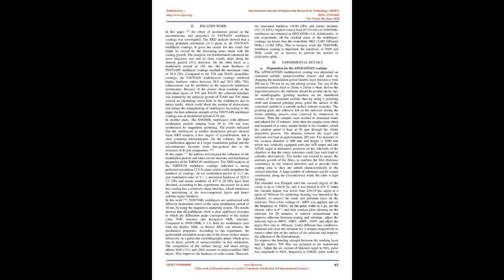In another study, the HfN/HfB2 multilayers with different modulation periods ranging from 20 to 150 nm were synthesized by magnetron sputtering. The results indicated that the multilayers at smaller modulation periods showed weak XRD textures, a low degree of crystallization, and a clear columnar microstructure. On the contrary, the high crystallization appears at a larger modulation period and the microstructure becomes more fine-grained due to the existence of B-rich components. 16. In this paper 17, the authors investigated the influence of the modulation periods and ratios on the structure and